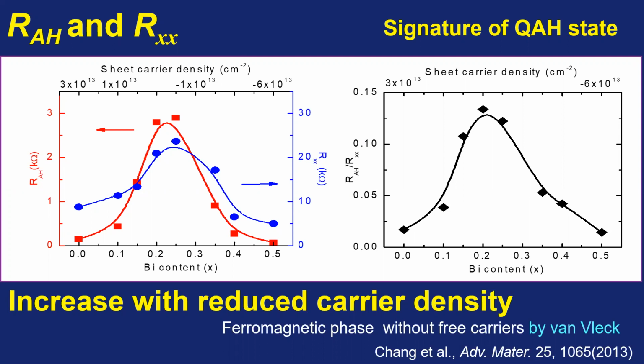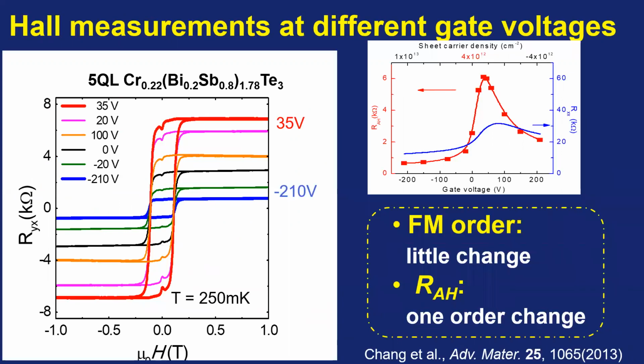The reason we can realize this kind of phenomenon in the magnetic doped TI is because the ferromagnetism in this kind of magnetic doped TI is induced by the Van Vleck mechanism, not as in the conventional diluted magnetic semiconductor, where it's usually induced by the RKKY, which depends on the carrier density of the sample. So the second step is we use the gating effect. We know that using chemical doping is very difficult to finely tune the chemical potential to the magnetic exchange gap. So we introduce the gating effect.